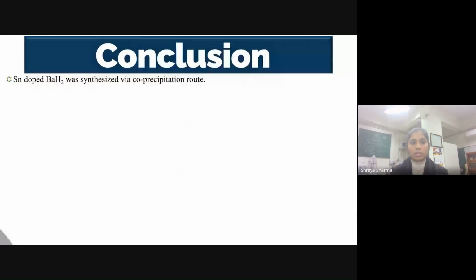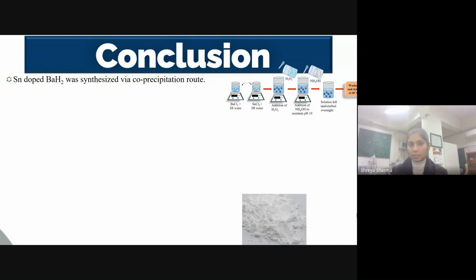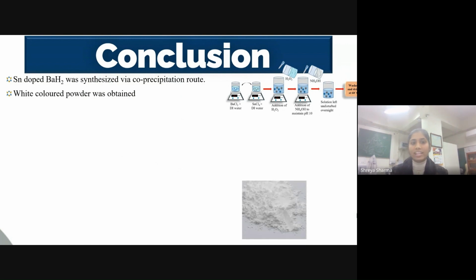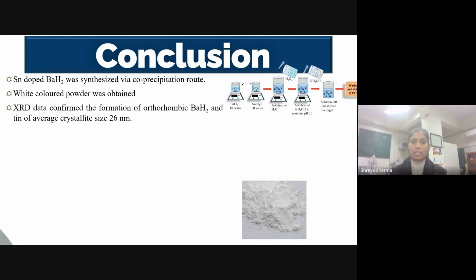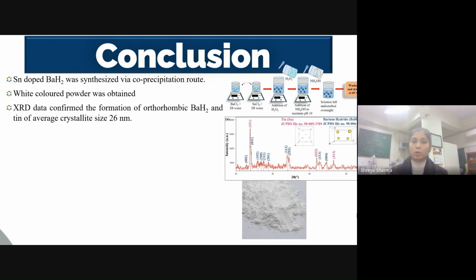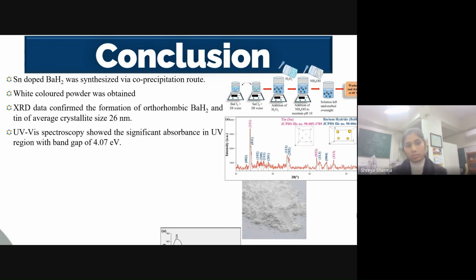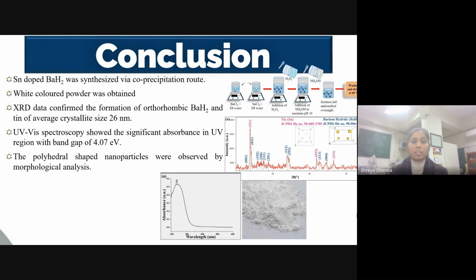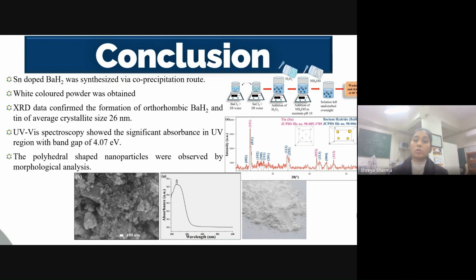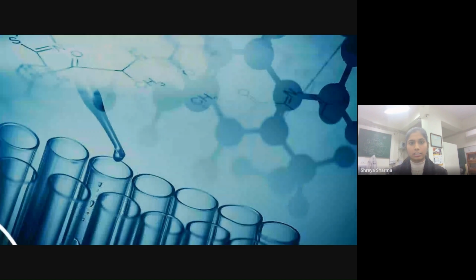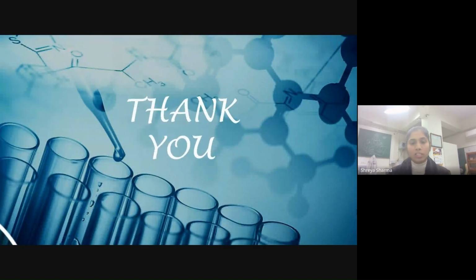Finally, moving on to the conclusion part, I can say that tin-doped barium hydride was synthesized via the co-precipitation route, and a white-colored powder was obtained by the synthesis method. XRD data confirmed the formation of orthorhombic barium hydride and tin of average crystallite size approximately 26 nanometers. UV spectroscopy showed significant absorbance in the UV region with a band gap of 4.07 electron volts, as can be seen here. The polyhedral shaped nanoparticles were also observed by morphological analysis. Thank you so much for your kind attention.